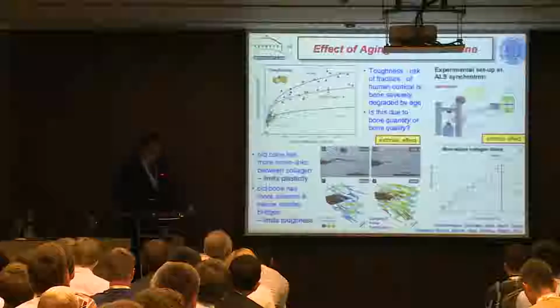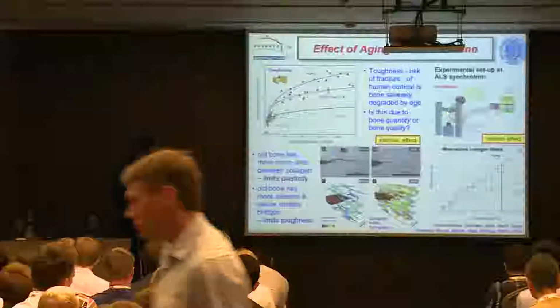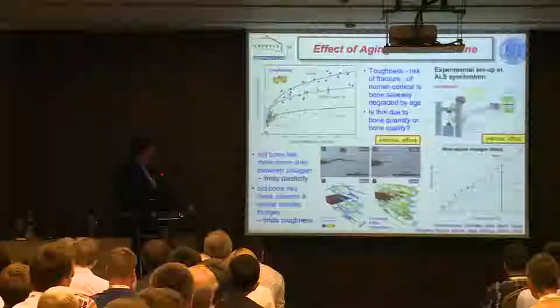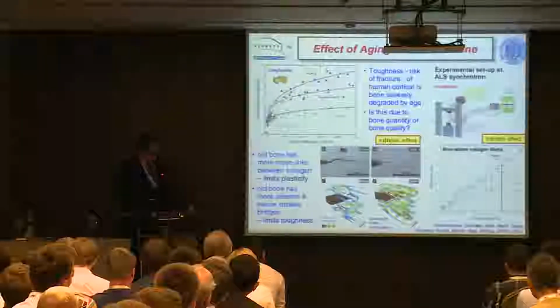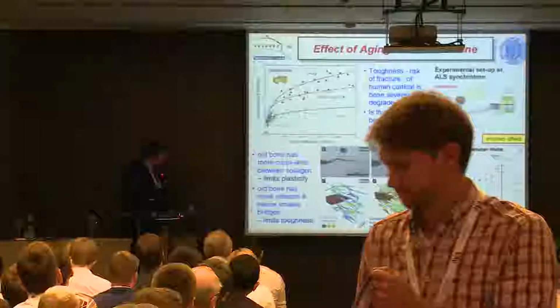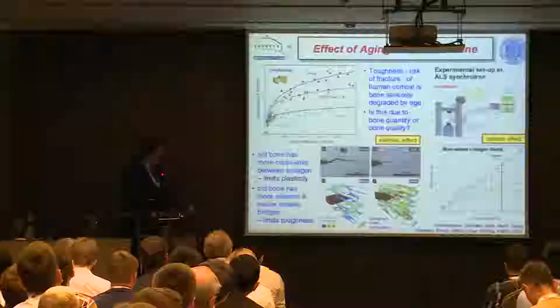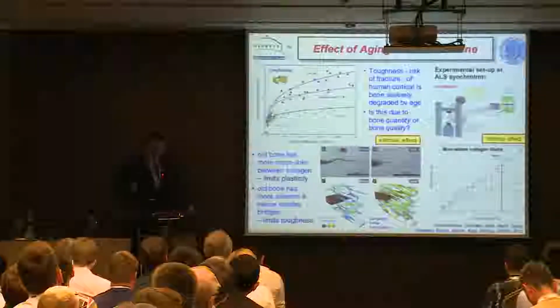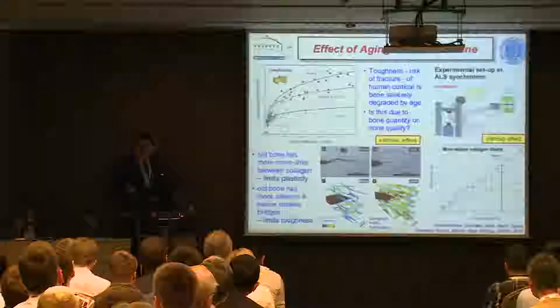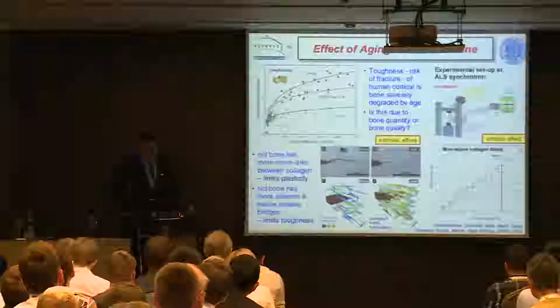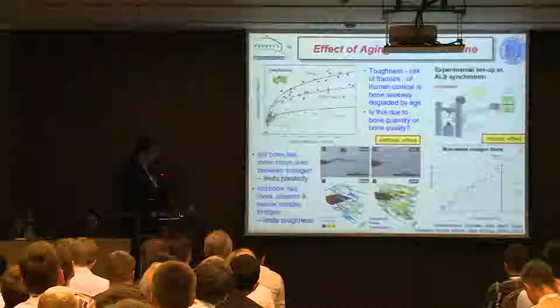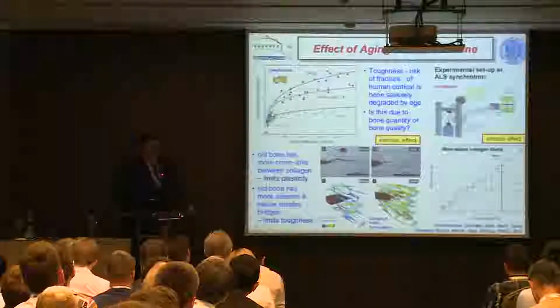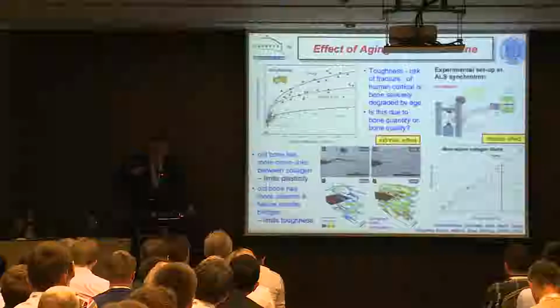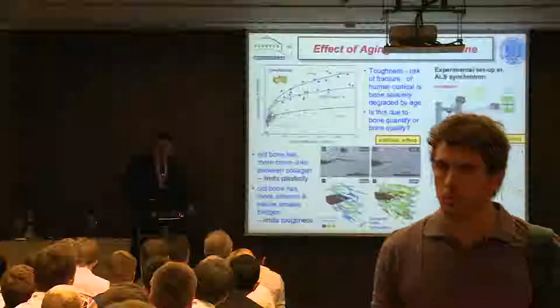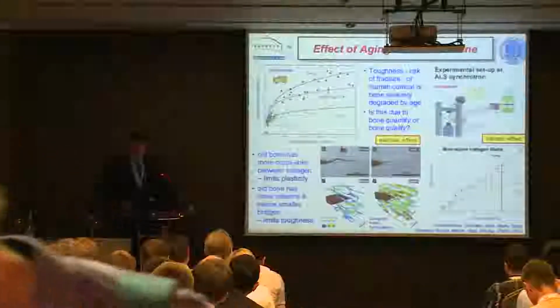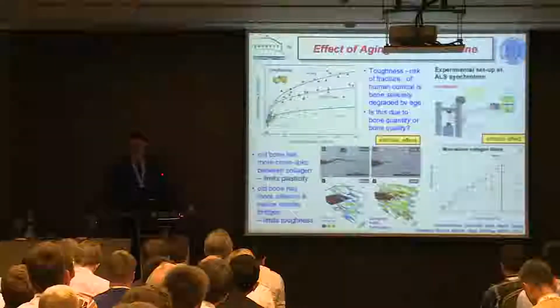The intrinsic part is interesting too. We can look at this. We do this in the synchrotron. We do a tensile test on a piece of bone in the synchrotron, and we're measuring here the strain in the bone. And we then do wide-angle X-ray diffraction, which is focused on the mineral, and we can get the strain in the mineral. That's not too important here. But we can also do small-angle X-ray scattering and look at the collagen. And since the mineral is very uniformly placed along the collagen, we can get a strain there as well. We can measure the strain in the collagen.